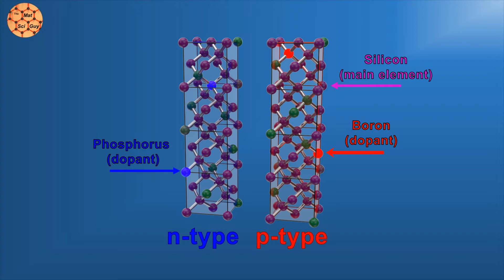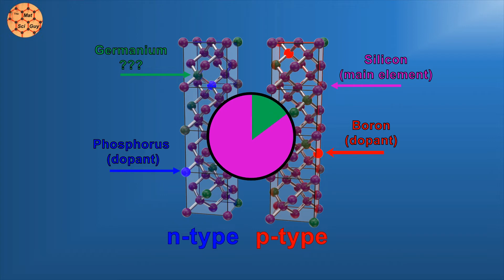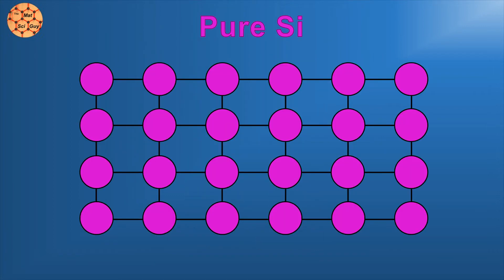But these doping processes are applicable to pure silicon, so it doesn't explain why silicon germanium is a better thermoelectric material. About 20 atomic percent of germanium is present in the most commonly used composition, and its role isn't quite as obvious at first. You see, part of the problem with using silicon, or any pure semi-conducting element, is that typically thermal conductivity is quite high. The phonons that contribute to thermal conductivity generally love crystal lattices that are pure and regularly ordered.